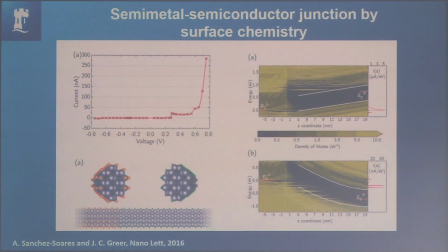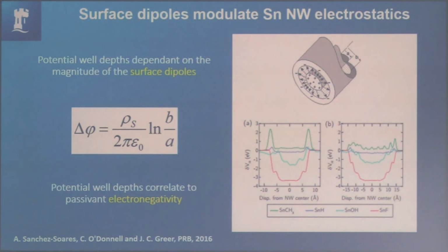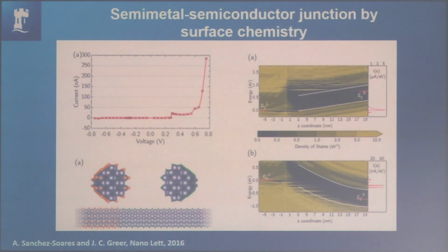So we said, okay, what you can do then is you can take the quantum confinement effect and make a very thin film, and if you choose your surface termination correctly, you can close the band gap. So I'm back to the situation where by taking a single material, if I can pattern one side with one surface termination and pattern the other side with another surface termination, I have a metal region next to a semiconducting region, and I haven't used any doping. We haven't actually done this experimentally yet, but we have done some calculations.